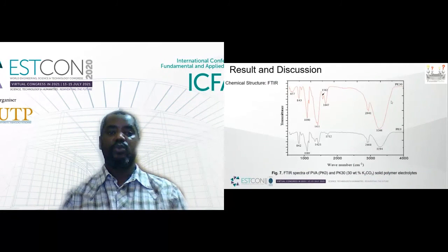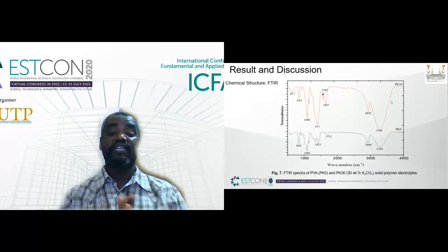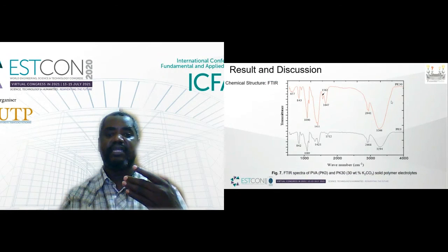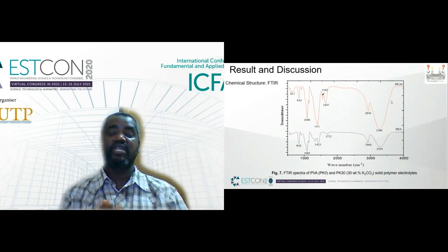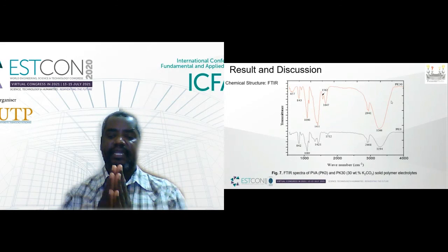Now, the results and discussion. We use FTIR in order to examine the changes between the polymer before incorporation of the salt and after the incorporation of the salt. It was reported that by blending the polymer and the salt, there will be extra sites for action and jumping of ions that make the ionic conductivity improve.